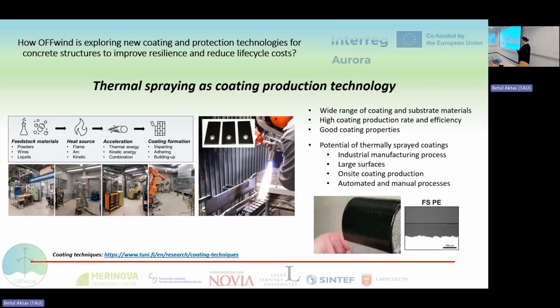And it's a process where we have a feedstock material, that what we want to have as a coating. It can be in the form of powder or wire. And then we have a heat source, so we are melting that material, and then we are accelerating that towards the surface where we want to build up the coating. And then these molten particles, they are hitting the surface, they are impacting and start to build up the coating. And it's a fast process. And we have good experimental facilities here to do these coatings. And it can be produced on different types of surfaces, here different geometries also. And that's why we consider this technology, because of these benefits, to use on these concrete materials.